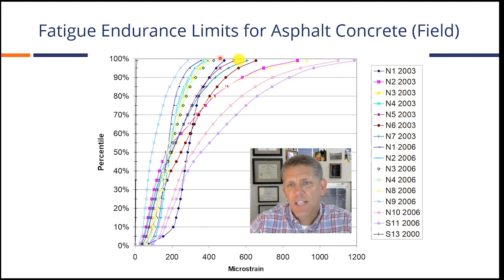So up here, this is the maximum strain that these sections saw. Down here, the 0% is the minimum. Say the average or the mean value of strain that was measured across all of these different pavement cross sections. And they represent different types of materials, different soil conditions, and so on at the test track. What was really interesting when you first look at a plot like this is it looks like a jumble of curves, and you have some that have high strain, some that have relatively low strain, and then everything in between.